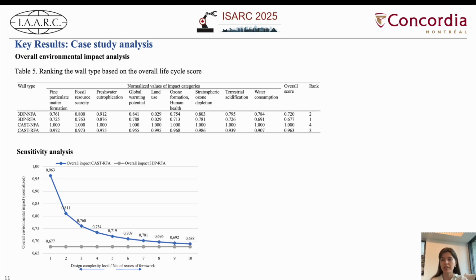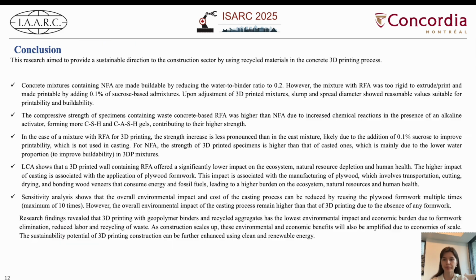So this demonstrates that 3D printing is not only more efficient, but also less sensitive to design complexity, making it a scalable solution for sustainable construction. We demonstrated that with small adjustments like lowering the water-to-binder ratio for natural resources and adding a small amount of sucrose for recycled ones, both printability and buildability could be achieved.